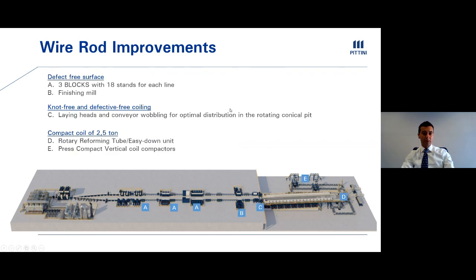There are other important improvements in our wire rod, which are connected mainly to surface, coiling, and coil weight. A surface has to be defect-free, and this is achieved again by the sizing mill that I have just mentioned, and by the 3 blocks for a total of 18 stands for each of the 2 lines. For what concerns coiling, in order to have a free and effective coil, this is possible due to the laying heads and the conveyor wobbling for an optimal distribution of the material in the rotating conical pit.